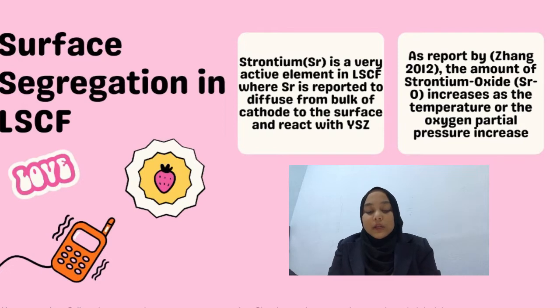Strontium is a very active element in LSCF. Strontium is reported to diffuse out from the bulk of the cathode to the surface and react with YSZ to form insulating strontium zirconate phases. The strontium-rich phase can be intrinsic and also be activated by the presence of impurities. Strontium segregation increases as the temperature increases and also when the oxygen partial pressure increases. However, experiments need to be done to clarify how strontium segregation is influenced by the conditions stated, and how the surface modification of LSCF cathode material is proposed in improving its stability plus reducing the surface segregation.